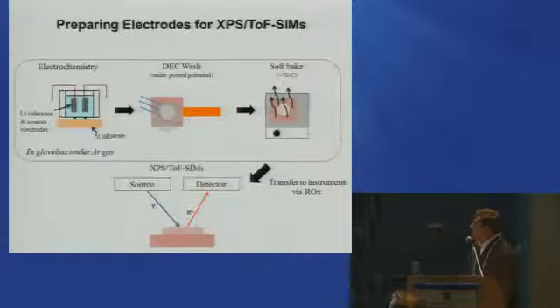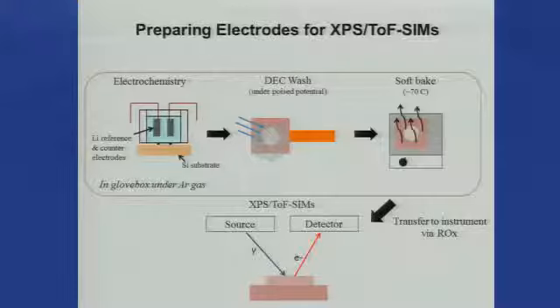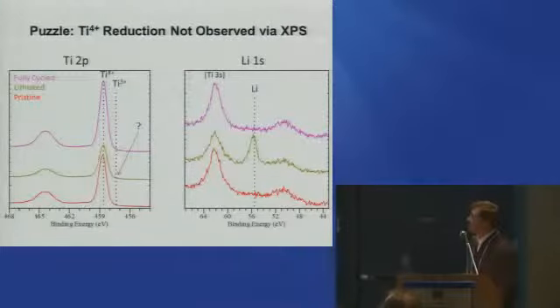And so this also requires a little bit of gentle treatment. We can wash this electrode from a flood cell taken from a glove box with DEC, which is known not to solubilize those surface products. And then we do a soft little gentle bake to get rid of any excess solvent. And then we can stick it into an XPS or TOF SIMS for the surface analysis.